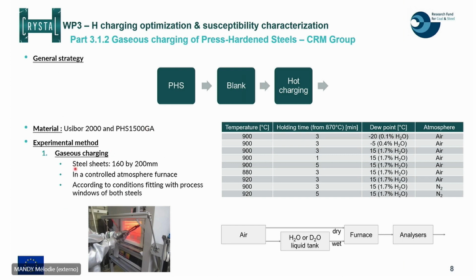In some words, for the gaseous charging, we worked with steel sheets, already cut, 160 millimeters by 200 millimeters. The gaseous charging consisted actually in an austenitization heat treatment that was performed in a controlled atmosphere furnace, according to specific conditions that we chose in order to fit with the process windows of both steels. So you see finally the conditions that were chosen here in the table on the right side. Globally the austenitization temperature was 900 degrees, or just below or just above. We have defined several holding times as soon as we reached a temperature of 870 degrees Celsius, and we tested also two other parameters of the atmosphere.